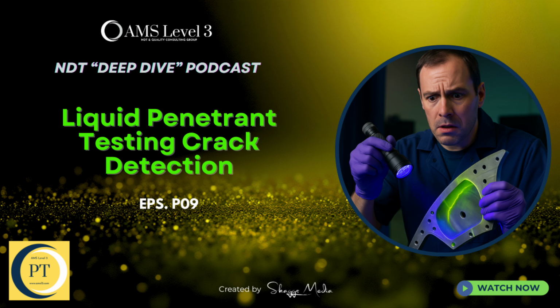Step 1, pre-cleaning and drying. I've heard people say this is the most critical part. Like, if you fail here, it's game over for the test. That is absolutely 100% correct. If that discontinuity is blocked by anything, could be oil, dirt, scale, even just moisture or residue from cleaning chemicals, the penetrant simply cannot get in. Adhesion fails, capillary action can't happen, the test is useless. Honestly, inadequate pre-cleaning, that's probably the #1 cause of false negatives, missing real flaws out in the field.